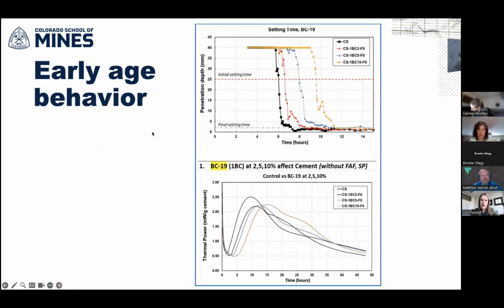So we're also looking at early age behavior. This is just work that's been done in the last month, so pretty preliminary, and we only have looked at one of the biochar samples out of the 16 so far. We do see some set time delays with inclusion of biochar. So in this top plot here, we go from 2, 5, and 10% from the red, blue, and yellow curves. And so you can see that our initial set time increases with the inclusion of biochar.